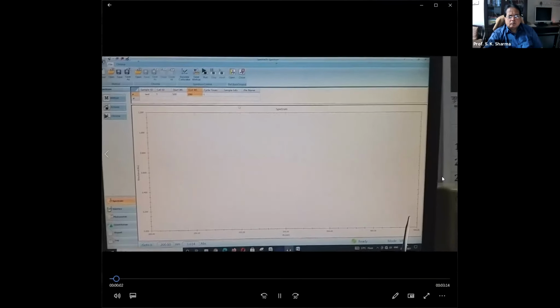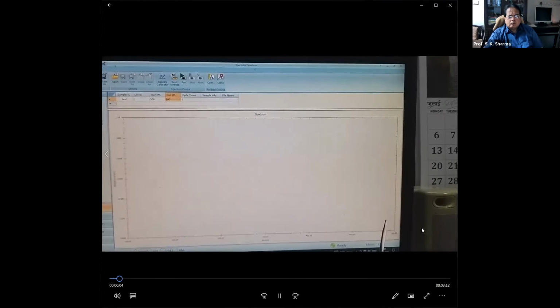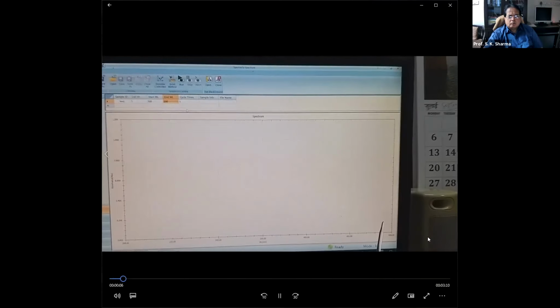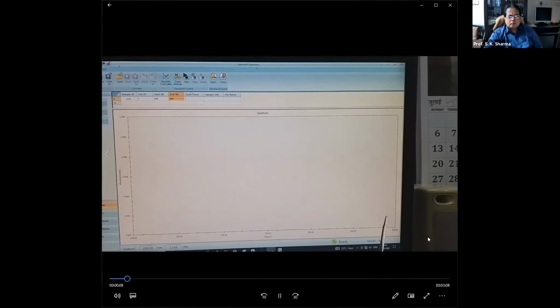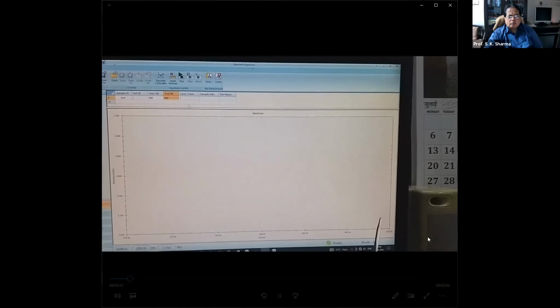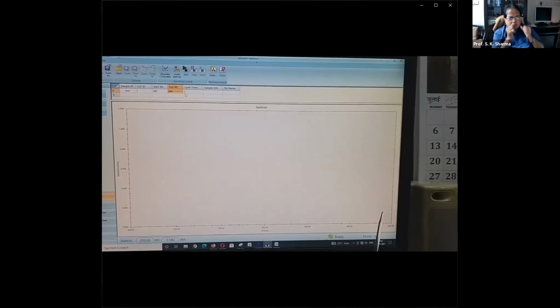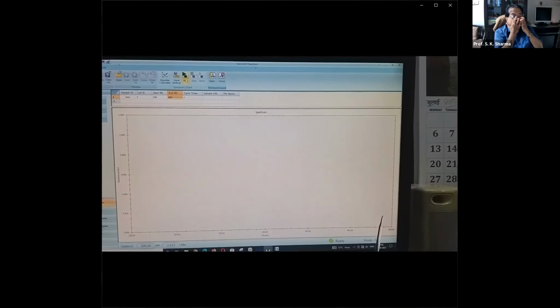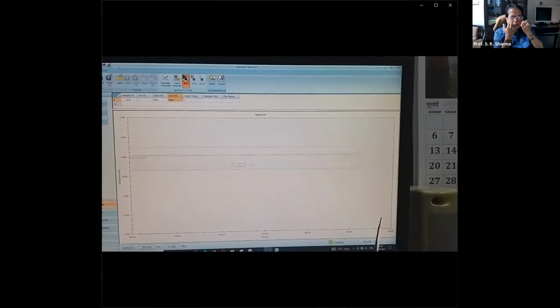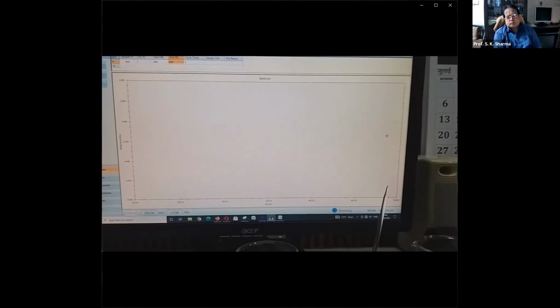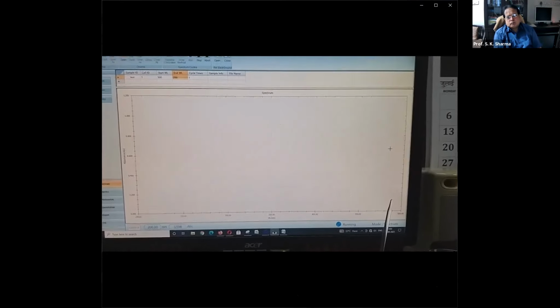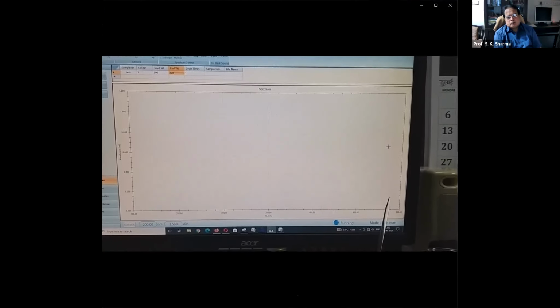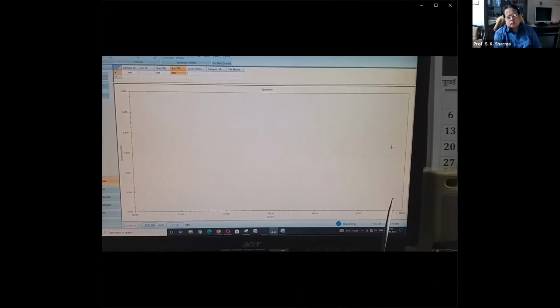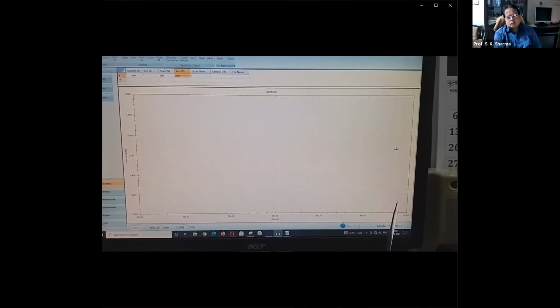So we are restarting the measurement because in our earlier experiment the concentration was too high, so we have diluted the solution and we are again running the same experimental measurement from 200 to 500 nanometers, and you are seeing the recording of the spectrum.